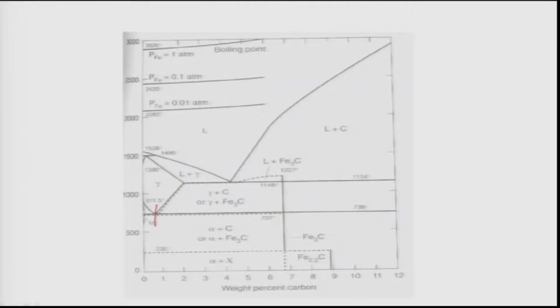The transformation can be easily shown. This transformation I am discussing happens at about 727 degrees Celsius, in which the gamma transforms to alpha plus Fe3C. This is similar to the reaction which I wrote, gamma going to alpha plus beta. Here alpha is alpha iron, and Fe3C is beta. This transformation is important in all steels, because steel has a composition between 0 and 1 weight percent carbon. That is why the physical metallurgy of steel basically revolves around understanding these reactions. That is what we will see.